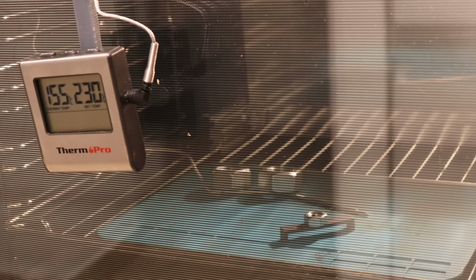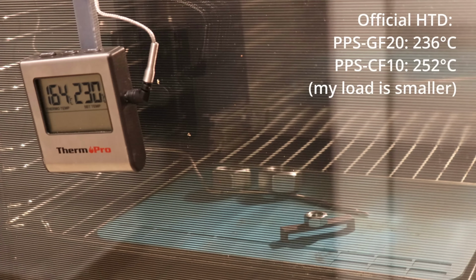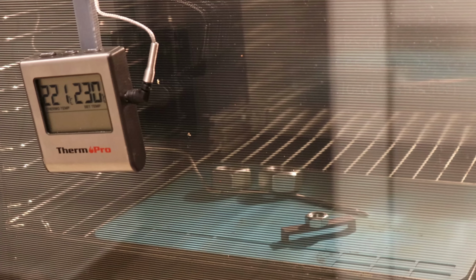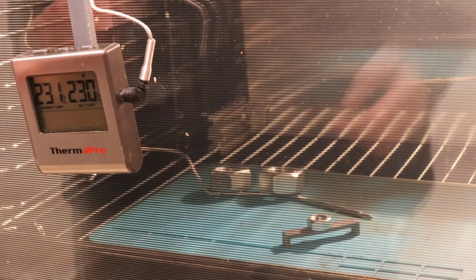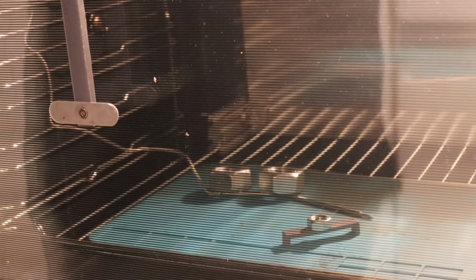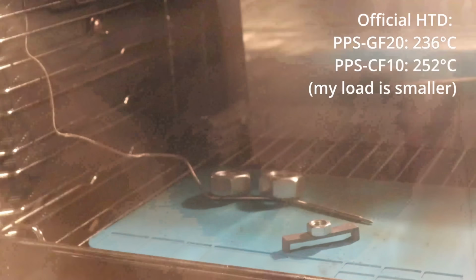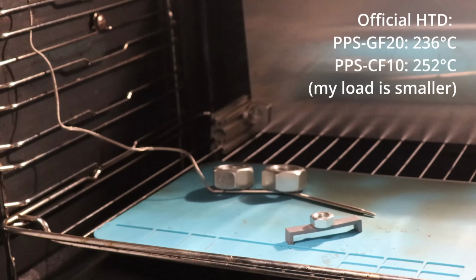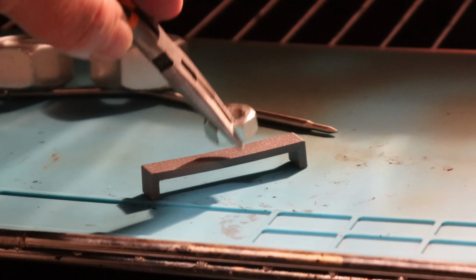And now one useless experiment, temperature test in the oven, where I want to record the temperature of the first noticeable deformation, but the maximum temperature of my equipment is not enough for this material. My tests don't follow any standards, an official ISO 75 load is 4 times bigger. So here I would advise to follow Polymaker's results, and in this case, the carbon fiber version is better.